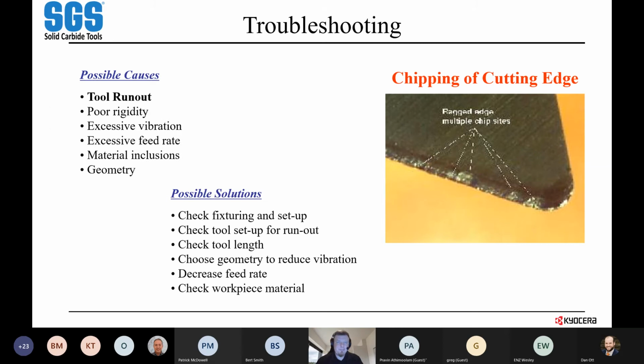Chipping of the cutting edge. There's a lot of different causes for this. You'll see tool runout being an issue, rigidity in both the setup and the tool itself. If your part's bouncing back and forth because your work holding isn't strong enough or rigid enough, or your tool has too much hangout or projection and it's bouncing off of the part, that's going to cause chipping, because that tool is going to come in and bite a little bit heavier on one flute and then bounce back out, cut lighter, and then come back in and cut heavier with the next flute.